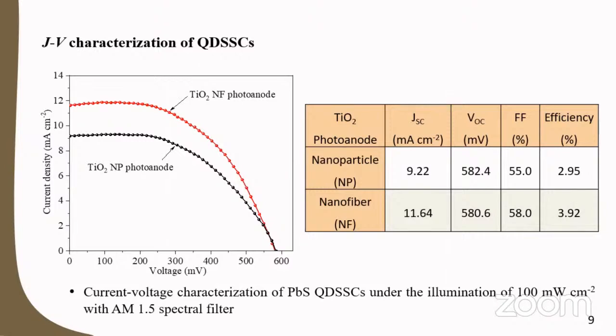This figure shows the current voltage characteristics of PbS QDSSCs fabricated with TiO2 nanoparticle layer photoanode and TiO2 nanofiber photoanode under the light illumination. TiO2 nanofiber photoanode shows better photovoltaic performance than TiO2 nanoparticle photoanode, as shown here. QDSSC with TiO2 nanofiber shows about 11.64 milliampere per square centimeter current density, while QDSSC with nanoparticle shows only 9.22 milliampere per square centimeter current density.